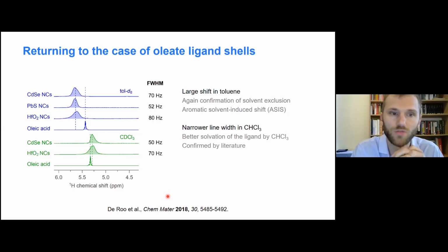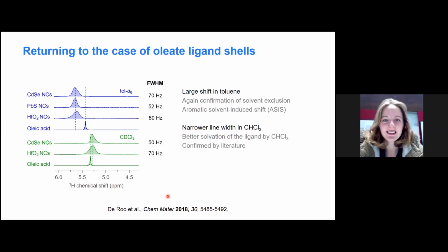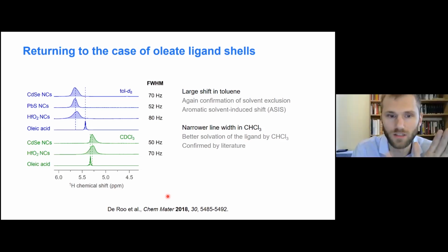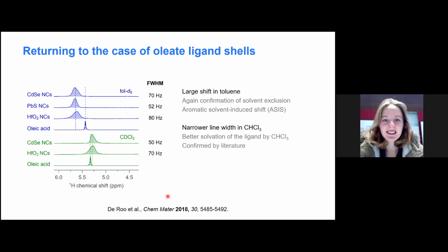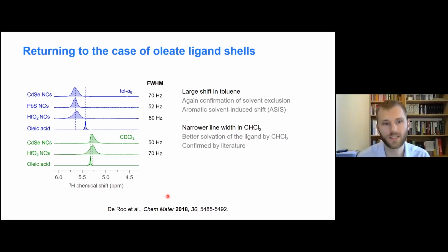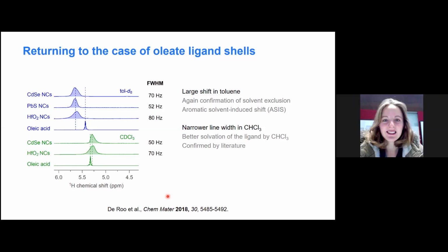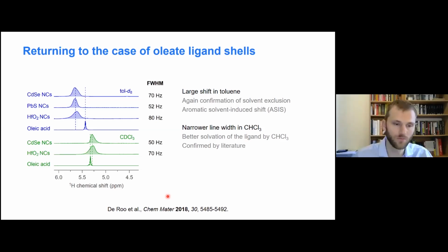That is not true. That is true for some nanocrystals, but it really depends on the nanocrystal-ligand combination. In the case of cesium lead bromide with those oleylammonium ligands, they are really, really labile. So there it's impossible to get a monolayer of ligands on the surface. In the case of carboxylates, that is often possible. So in the case of cadmium selenide, in the case of hafnium oxide, it is really possible to purify well and remove all free ligands, and there's then one monolayer remaining on the surface.